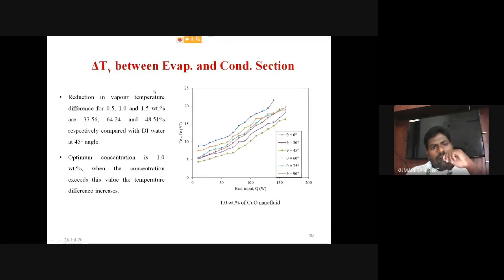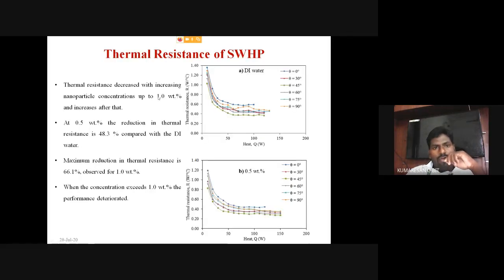Next, the vapor temperature difference between the evaporator and condenser sections. You see here that at the horizontal position, for 0-degree inclination, the vapor temperature difference is somewhat high compared with other positions. When we tilt the heat pipe up to 45-degree inclination, the best, optimized performance of the heat pipe is attained at 45-degree orientation. The next one is the thermal resistance of the heat pipe. The thermal resistance decreased with increasing nanoparticle concentration up to 1 weight percentage and increased after that.